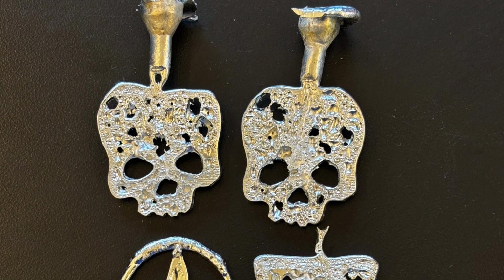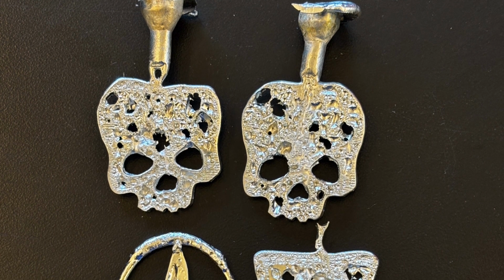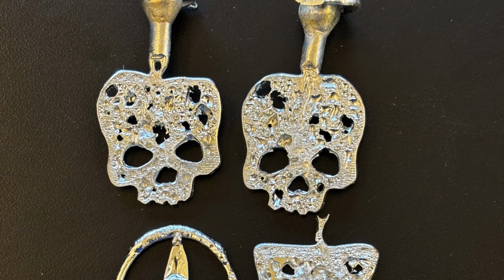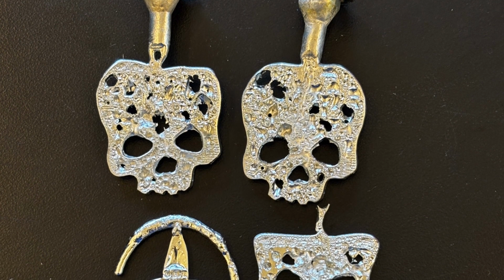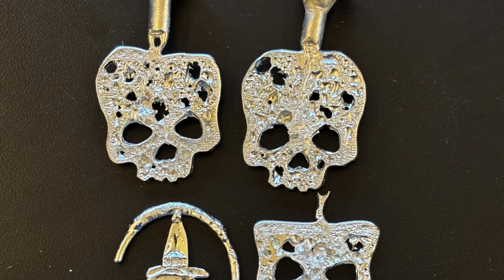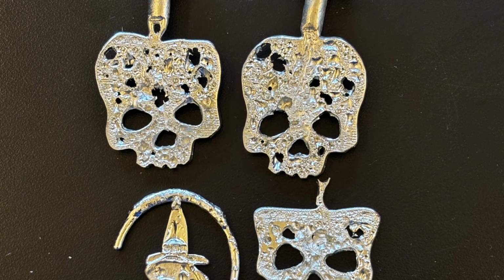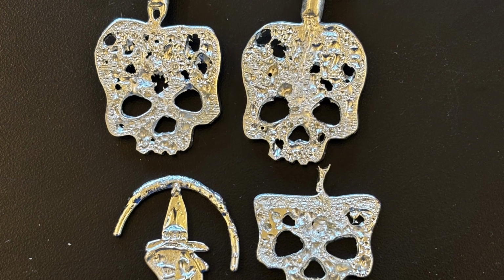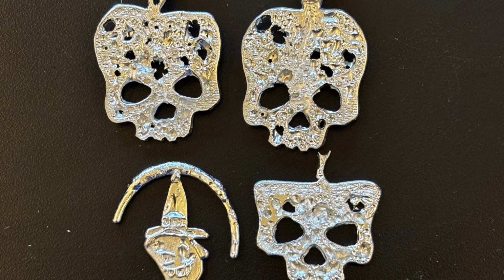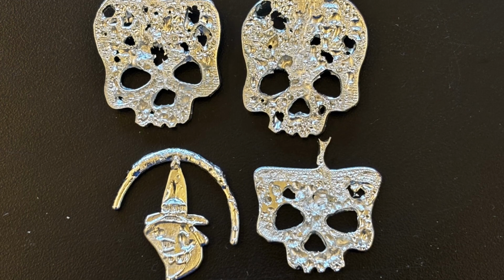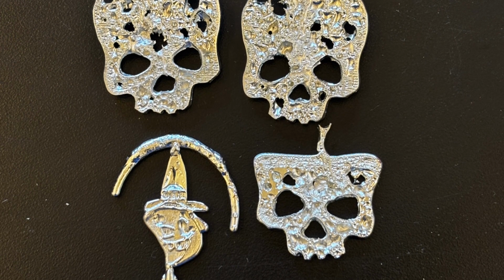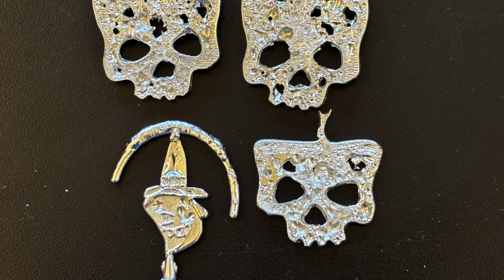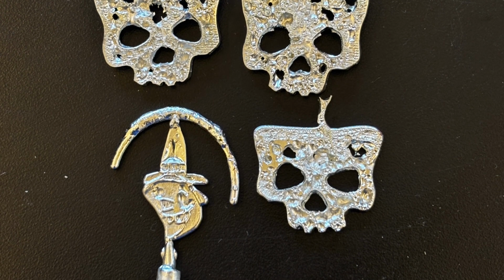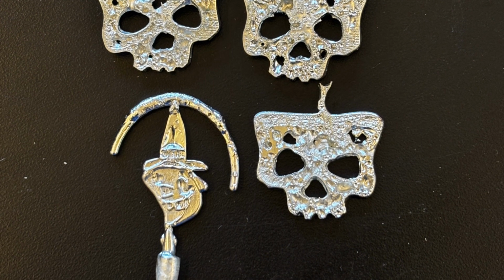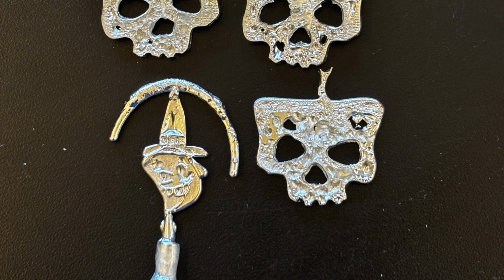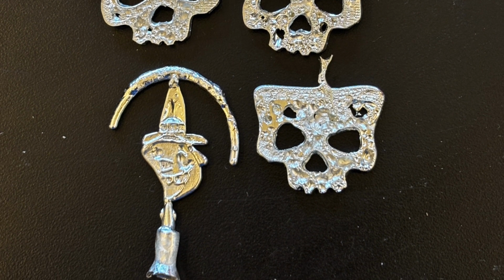Now, if you don't use talc in your mold and just jump right in and cast your pewter, you're going to get these kind of castings that have this, what I think is actually really interesting, bizarre porosity in the castings. And in this case, with the sort of the Halloween theme, I think it fits in nicely, and you could do that on purpose, but it's certainly not very controllable at all and can cause other sorts of defects in the casting. So keep that in mind, but you need just very, very little talc, and that is going to cause a significant difference.